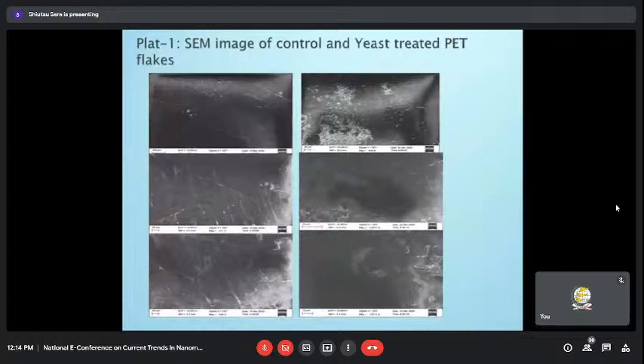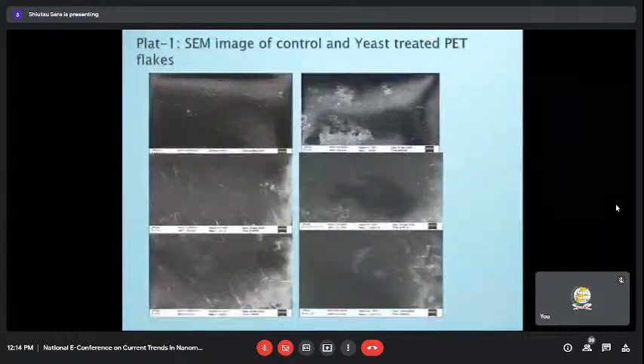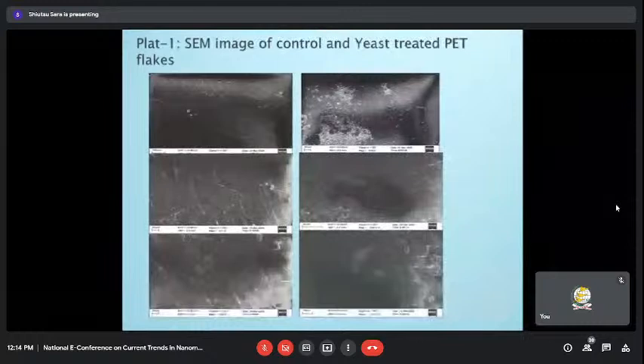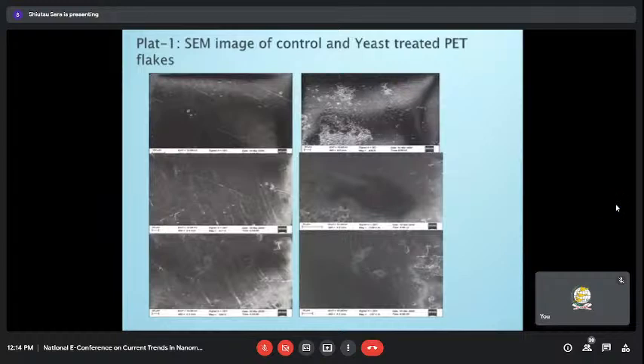The left side of this image shows the pictures of the samples which were not treated with the bacteria yeast, and the right side of the picture shows the samples which were treated with the bacteria yeast. Comparing between these two, on the right side of the image we can see some white patches occurring on the surface of the plastic, and also some formations of structures on the surface, as compared to the control sample. In the control sample, we do not see anything like that. So this is the evidence that growth of the bacteria yeast has taken place.